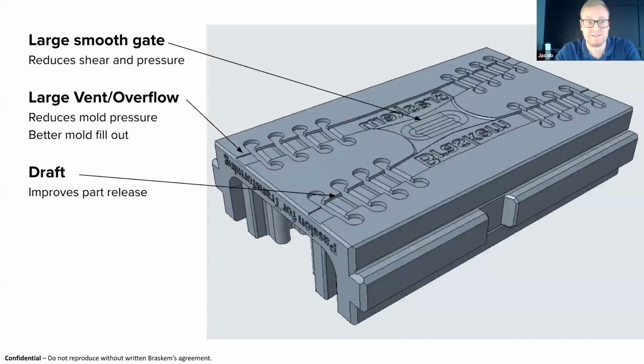So specifically right off the gate, no pun intended, a large gate is much more advantageous whenever you're working with a 3D printed mold. Again, you're reducing pressure where you have a larger flow path. You're reducing shear by increasing the volume for flow. Any opportunities you have to round off surfaces, as you can see in my CAD drawing here, it's going to help reduce shear and wear over time.